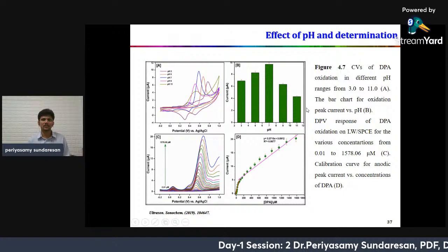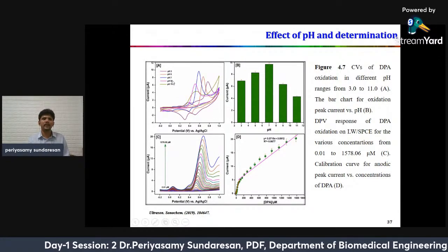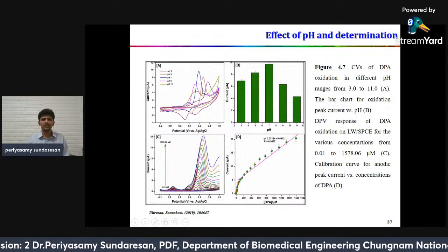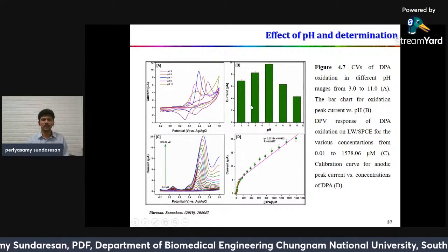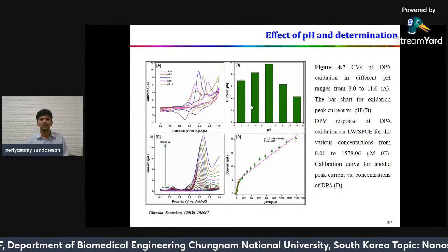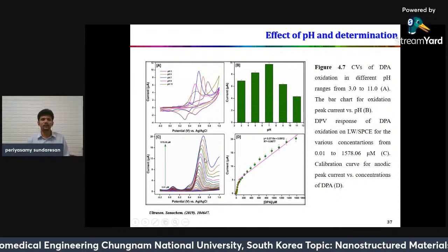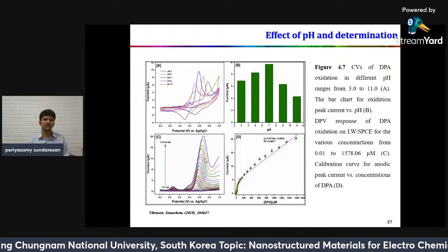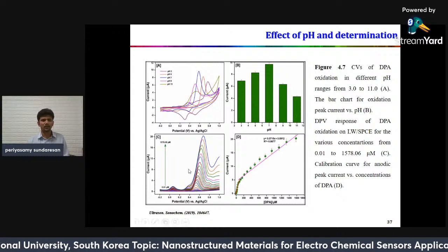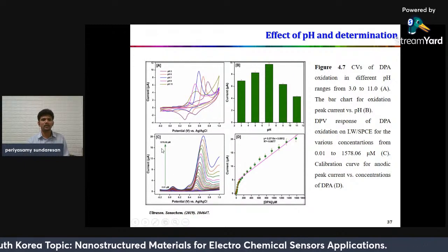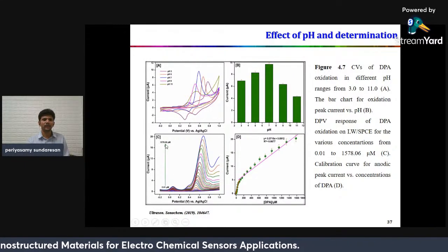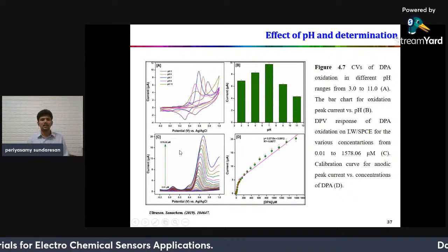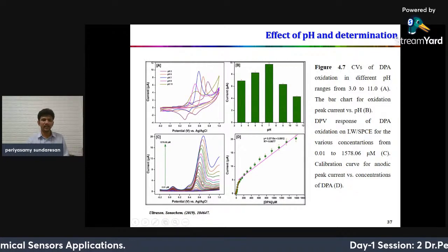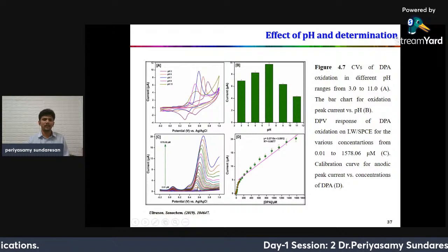For the effect of pH on the determination, I have checked 5 different pH values, but comparatively pH 7 gives a high current response. That's why I selected pH 7 for my work. This is the differential pulse voltammetric determination study. I have checked 0.01 to 1578.06 micromolar concentrations. The concentrations are linearly increased and the current also linearly increases.